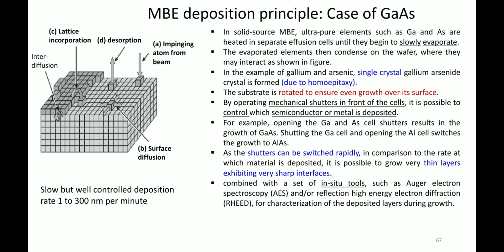Okay, so the interface is very important, because suppose your thin film's thickness is in the range of 5 nanometer gallium arsenide, 5 nanometer aluminum arsenide, 5 nanometer gallium arsenide. In that case the interface is nothing but the place exactly where the gallium arsenide is going to end and aluminum arsenide is going to start. So they should be sharp. Okay, they are sharp because the shuttering process is quite fast. So what you are getting is a very sharp interface, and this can all be controlled with the help of computers.